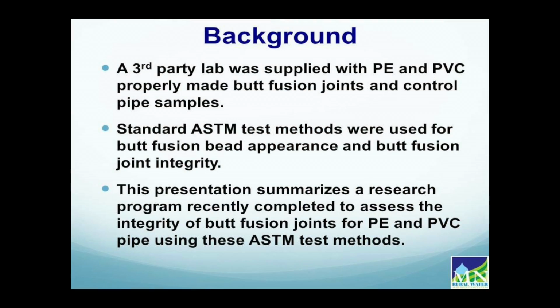In our research study, a third-party laboratory was supplied with polyethylene and PVC properly made butt fusion joints and the corresponding control pipe samples. It's always important, when you want to look at joint integrity, to take whatever the joint is and compare it to the parent material. We looked at standard ASTM test methods, we looked at the bead appearance, and we used these test methods to determine the integrity of the joint. Now we're going to summarize the program that was just completed to assess the butt fusion integrity for polyethylene and PVC butt fusion joints using these test methods.